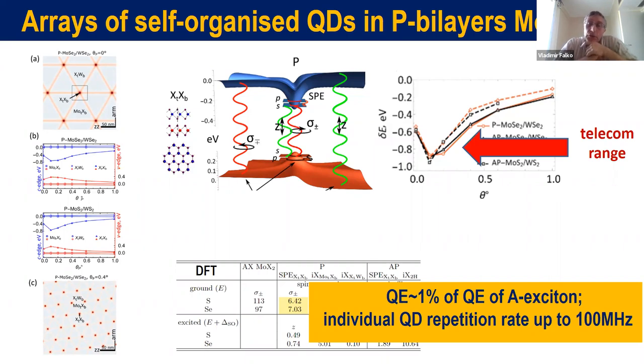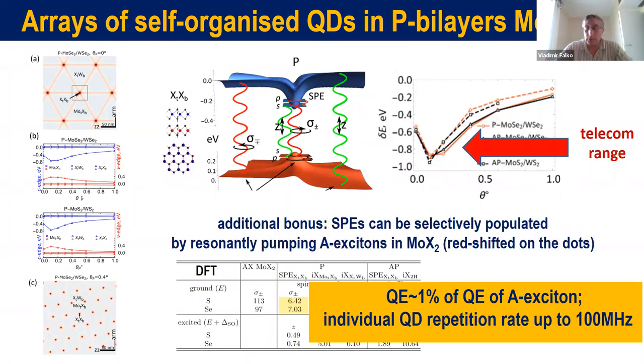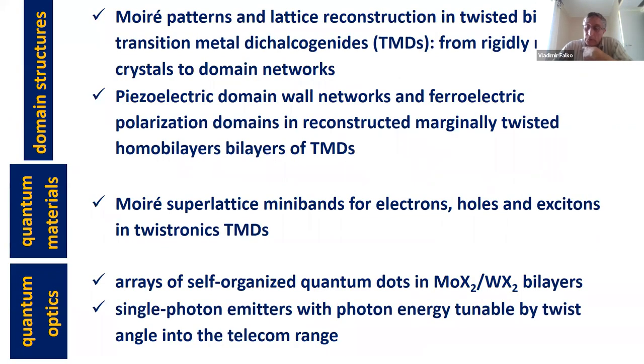And for those quantum dots, we therefore expect that there might be a maximum repetition rate for the light emission for heavily pumped dots going into the range of 100 megahertz, which is quite a good repetition rate for generating single photons. So this is the last thing that we got, and that's what I wanted to describe.